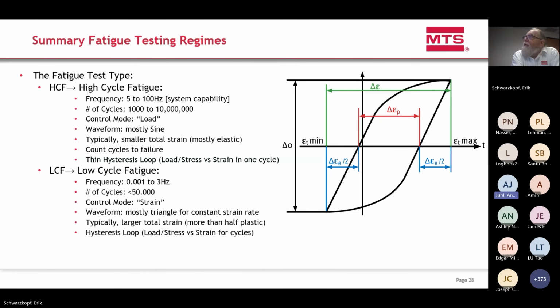The blue regions you can see down below that center line, that zero line, are the elastic strains, or a way to measure elastic strain. Elastic strain is essentially what we're talking about when we're talking about stress-controlled testing. And so we might expect a Basquin-type equation for the elastic strain, but something else for the plastic strain.